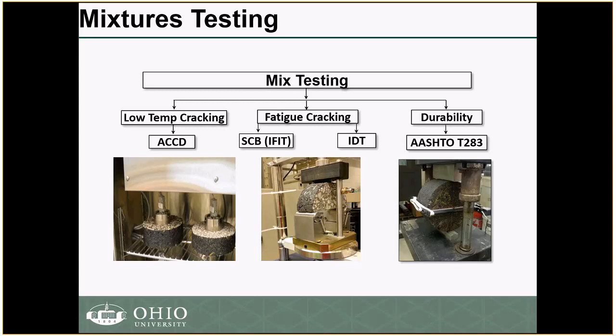We did ACCD, the asphalt concrete cracking device, for low temperature cracking. For fatigue cracking, we did SCB using the Illinois method, which is commonly referred to as the I-FIT. And then we did the indirect tensile strength, the modified Lottman or AASHTO T 283, for durability.